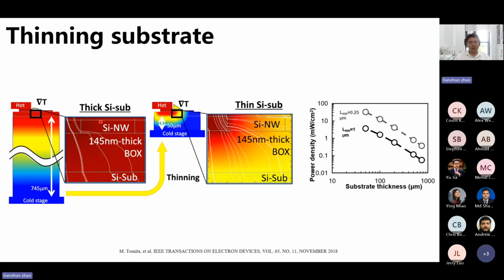And so first of all, we know that the thickness of the silicon substrate is very large. It's around 745 micrometer. So if we can thin the silicon substrate, we can change the temperature difference across the silicon nanowire, and then we can increase the power density. And so the simulation results show that the power density has been increased by more than 2 orders of magnitude.